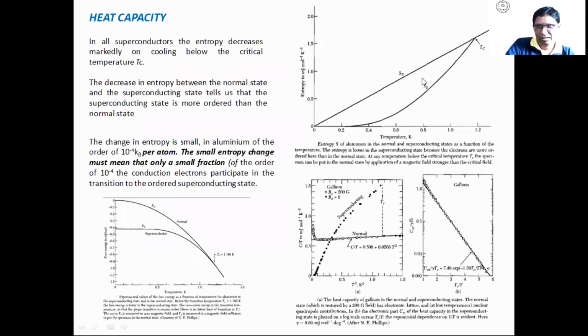As you measure the entropy of the superconductor, this is the graph of entropy for aluminum in normal state and superconducting state. This is the critical temperature Tc. This line corresponds to the entropy of the normal state of aluminum, and below it is the entropy of the superconducting state. You will see the entropy of the superconducting state is lower than the normal state. So one can conclude that the superconducting state is more ordered than the normal state.